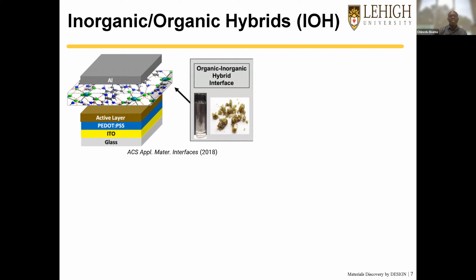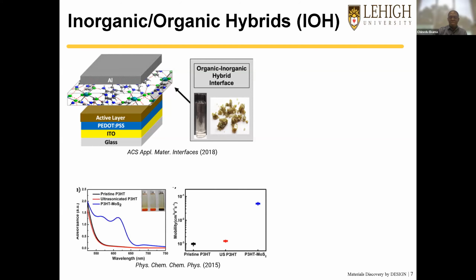So these organic and inorganic hybrid interfaces generally exhibit some novel physics, not all the time, but in our high throughput design, we end up running into a few that showed some optimized properties. As you can see here, this is pristine P3HT, and when you design the organic and inorganic molecule interface with MoS2, you can see enhanced optical absorption within this important wavelength. This is near infrared and visible light,